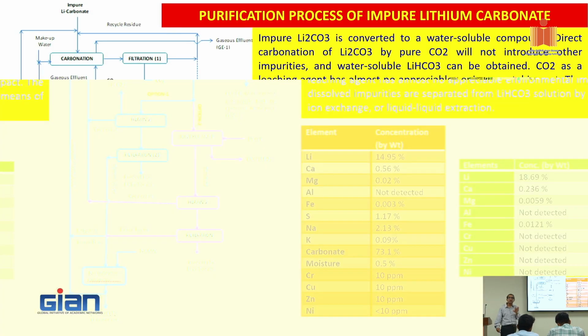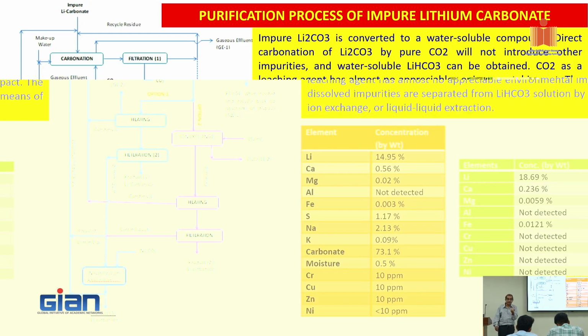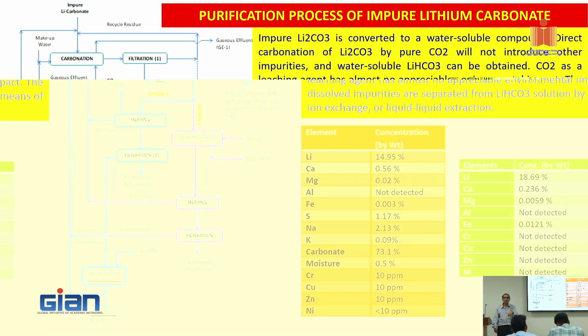After you get that, 14% grade lithium is only 80% pure, but you want 99 plus. So how do we do that? We take that pre-concentrated lithium carbonate from the first step of chemical processing and redissolve it by putting in carbonated solution. During that process, what will happen? Only lithium dissolves, rest.